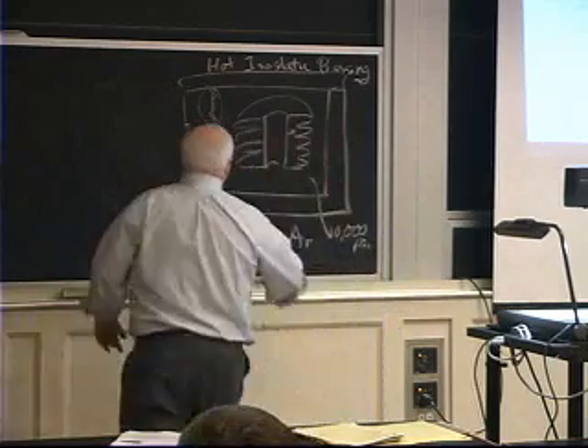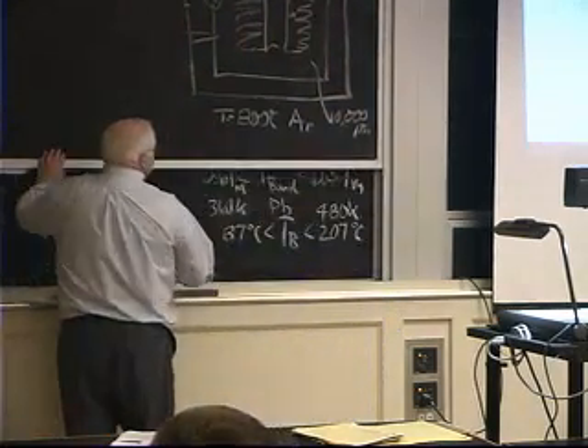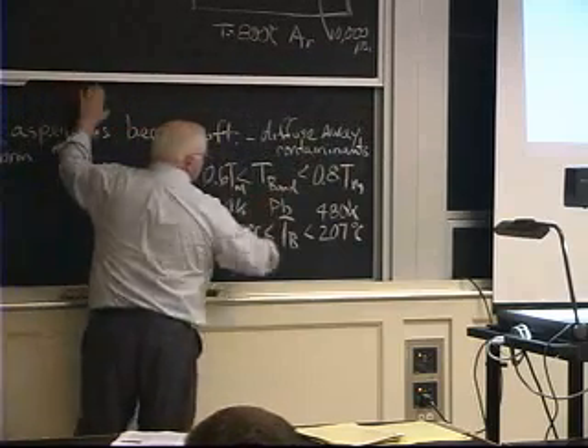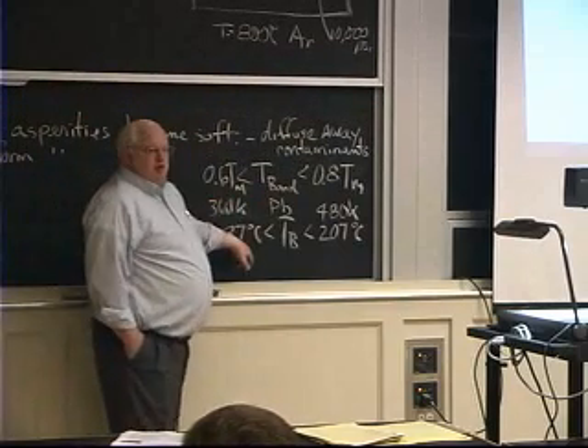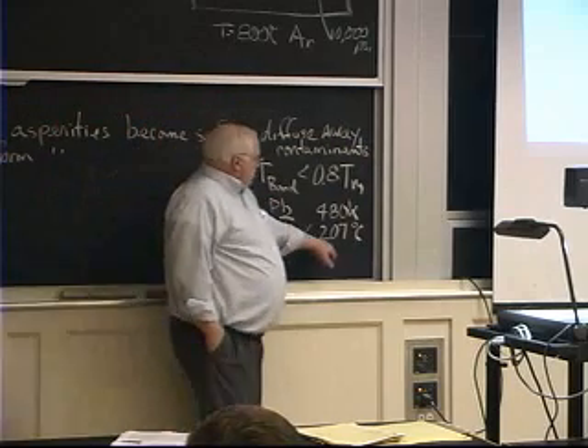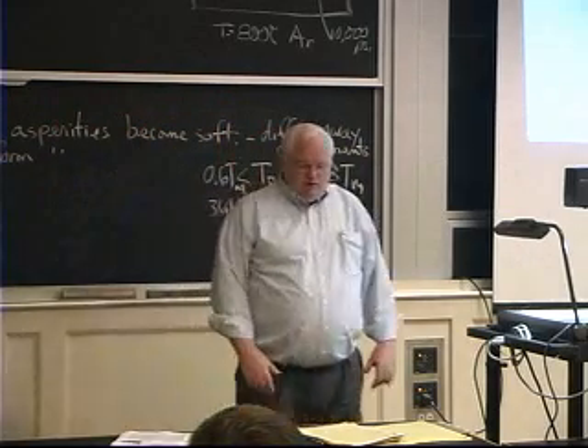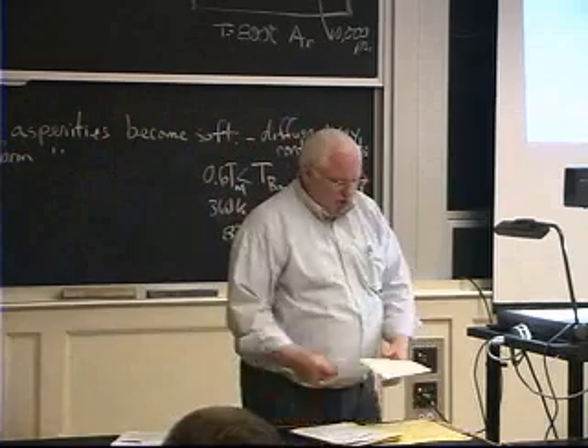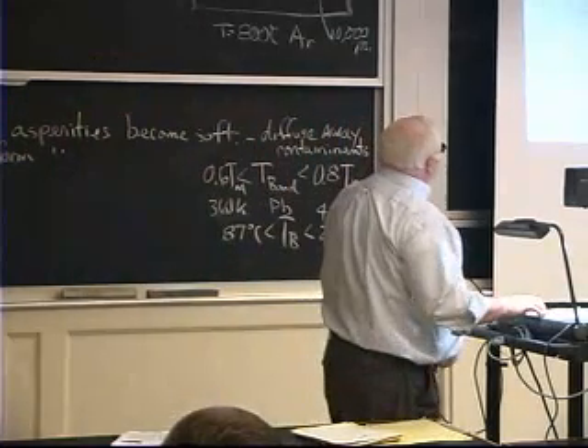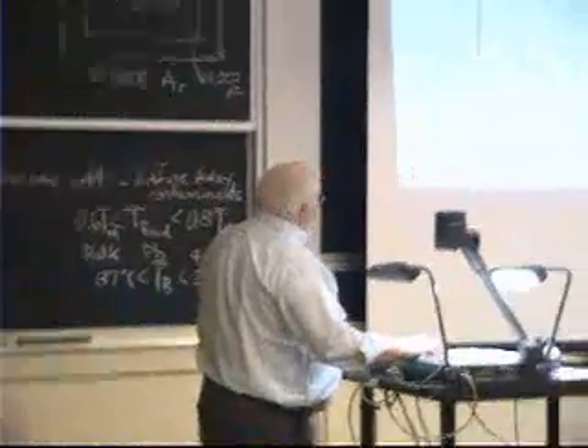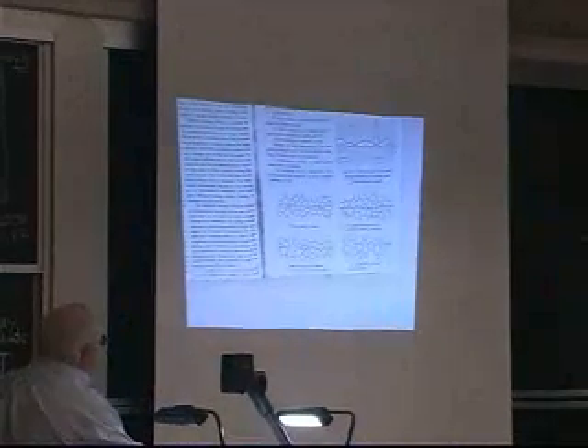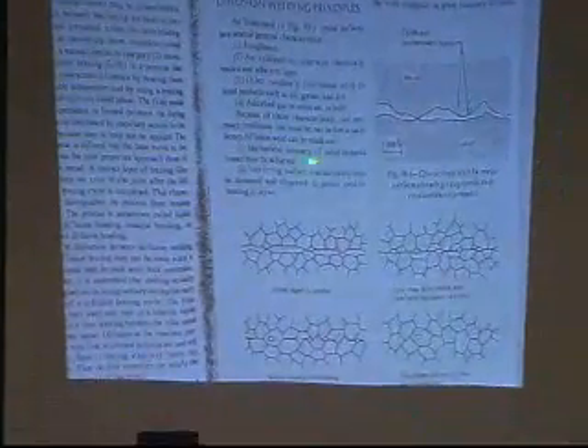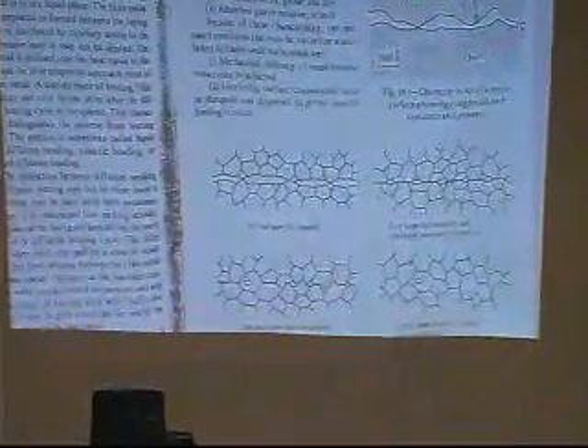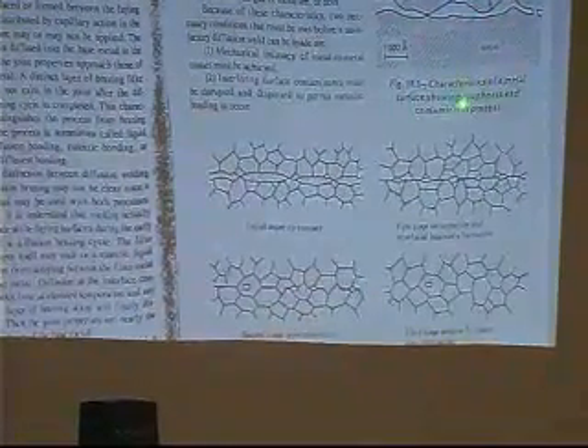But anyway, that's a way of diffusion bonding, if you will, on castings. But you have to get to a high temperature where you have enough temperature that the atoms will diffuse together. But the problem is you don't want to get to too high a temperature, because you get grain growth. And if you look at the old version of the welding handbook on diffusion welding and brazing, they have a handy-dandy little picture here that talks about the problems. And lo and behold, they got surface roughness, they got oxide and contaminant layers on the metal. This shows characteristics of a metal surface with roughness and contaminants. Gee, we talked about that, right?